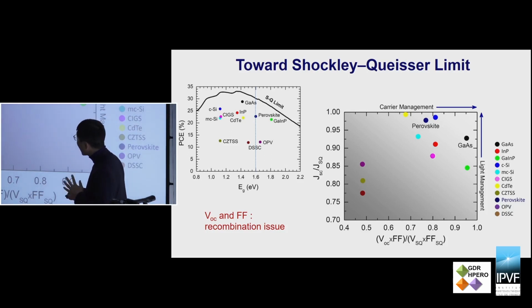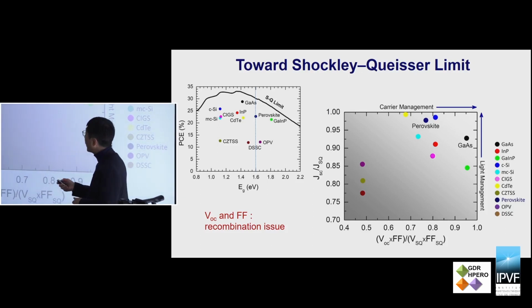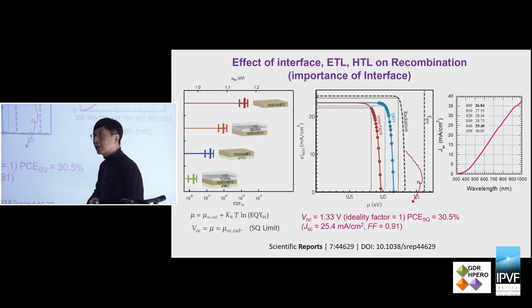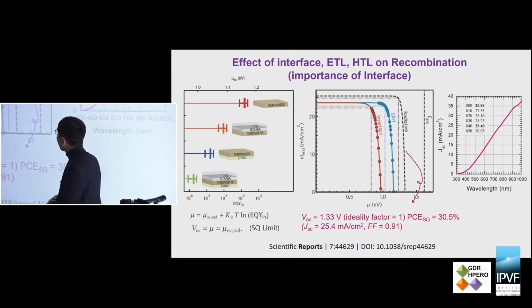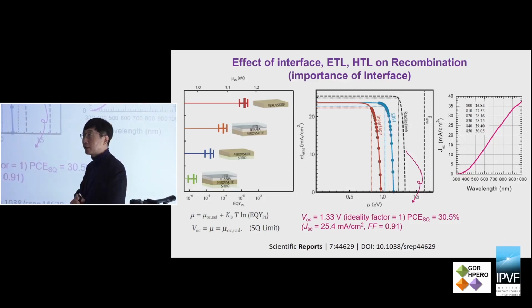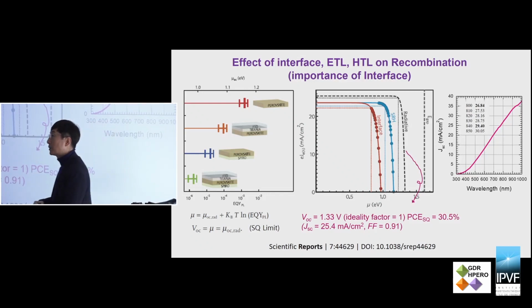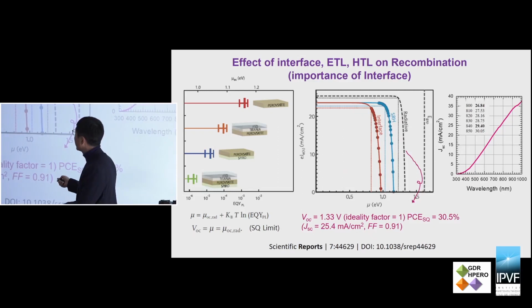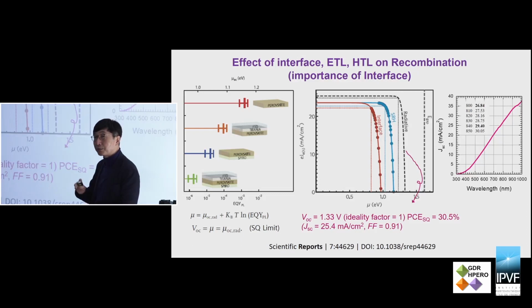The common issue limiting the open circuit voltage and fill factor is recombination, so we have to control the recombination. Here is a very good calculation result. For instance, if you use only the perovskite itself, without any interfaces, without any electron transport layer or hole transport layer, then you can get a high open circuit voltage. But once you introduce the ETL or HTL on both sides, the open circuit voltage decreases further. This mostly comes from interfacial recombination.